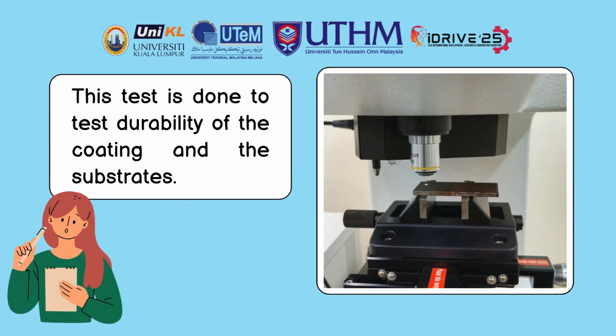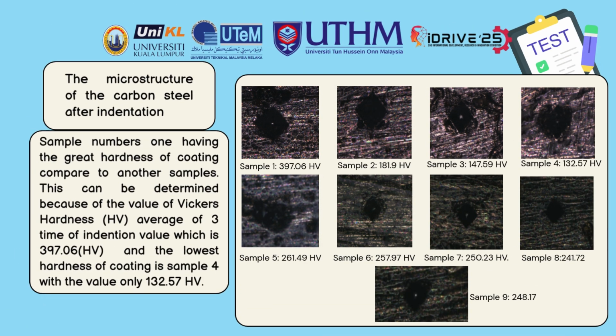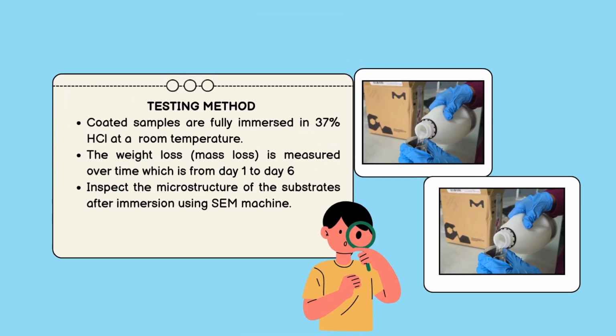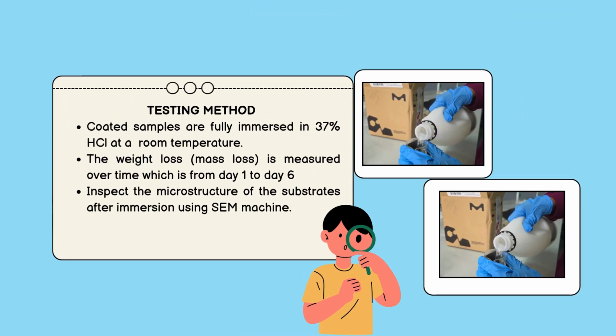This test is done to test durability of the coating and the substrates. The microstructure of the carbon steel after indentation. Sample number 1 has the greatest hardness of coating compared to the other samples. This can be determined from the Vickers hardness value, HV, the average of 3 indentation values, which is 397.06 HV, and the lowest hardness of coating is sample 4 with the value of only 132.57 HV.